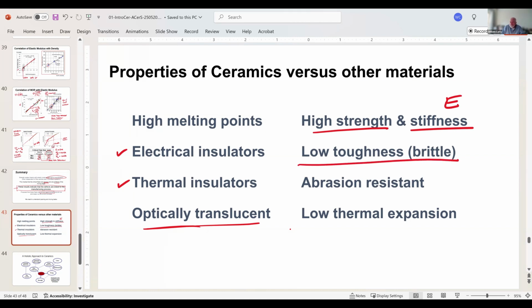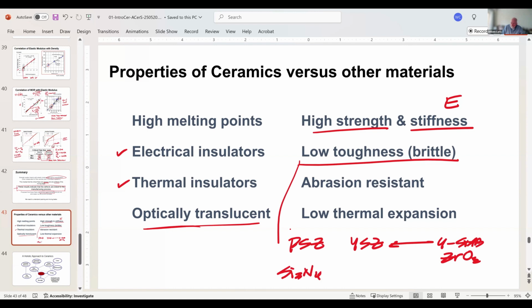The exceptions to this in terms of toughness are only two. The two exceptions are partially stabilized zirconia or yttria stabilized zirconia, and the other is silicon nitride. There are only two materials that have been developed in the 100 plus years of investigating ceramic materials that have high toughness. Everything else is brittle, and there are just no exceptions. The fracture toughness values are very low. We tend to be abrasion resistant because we are hard and resist damage, and we have a low thermal expansion coefficient.